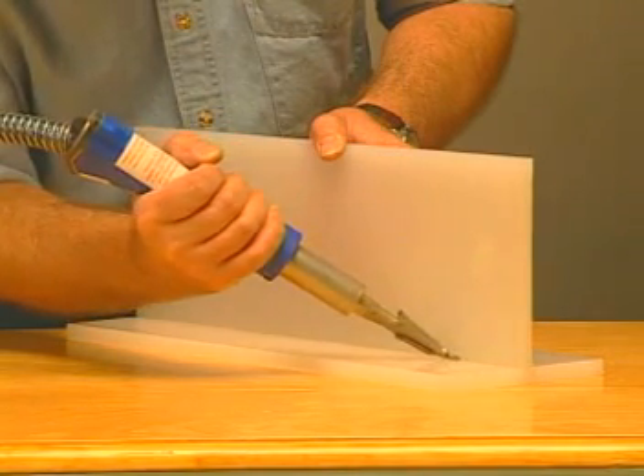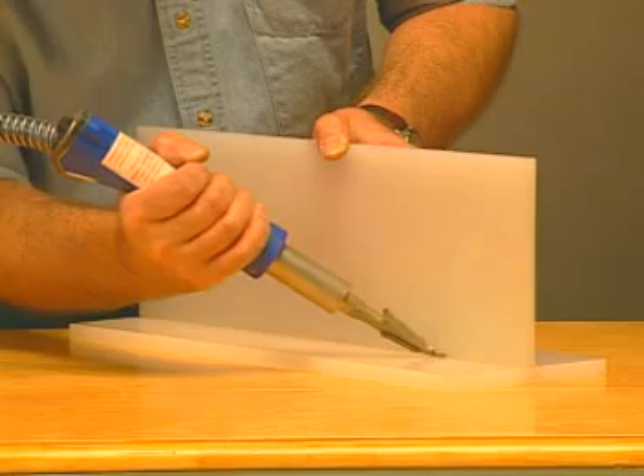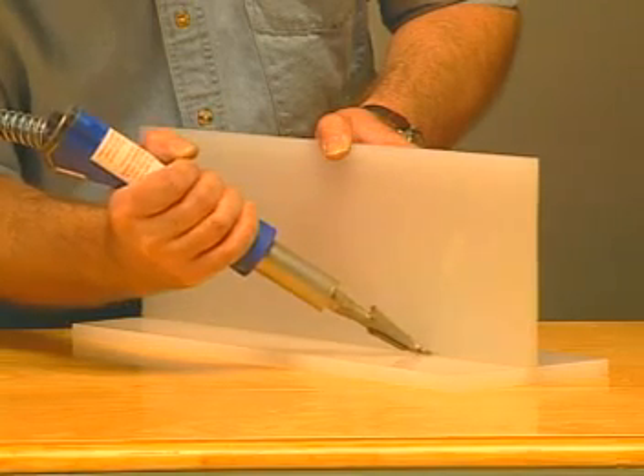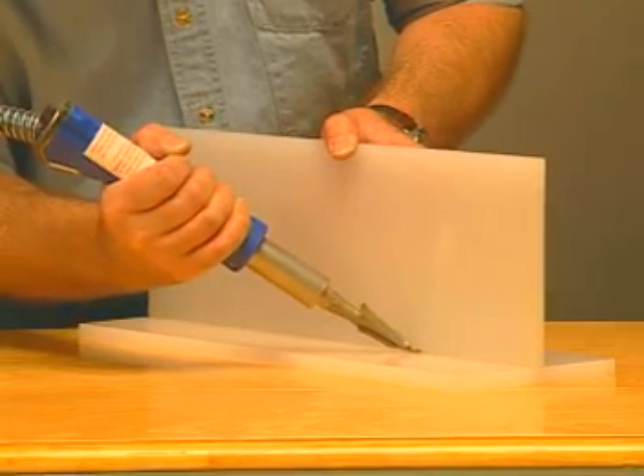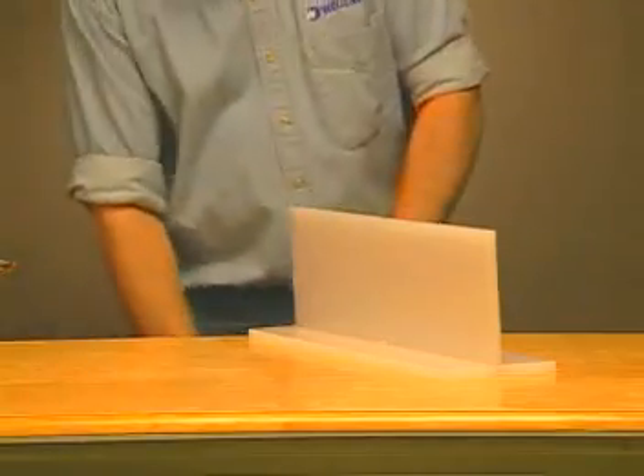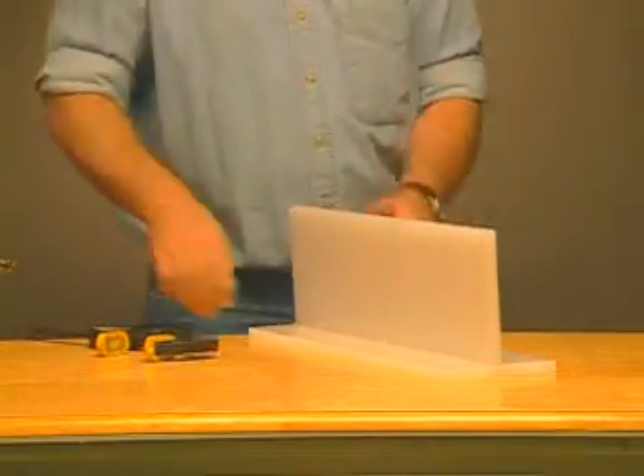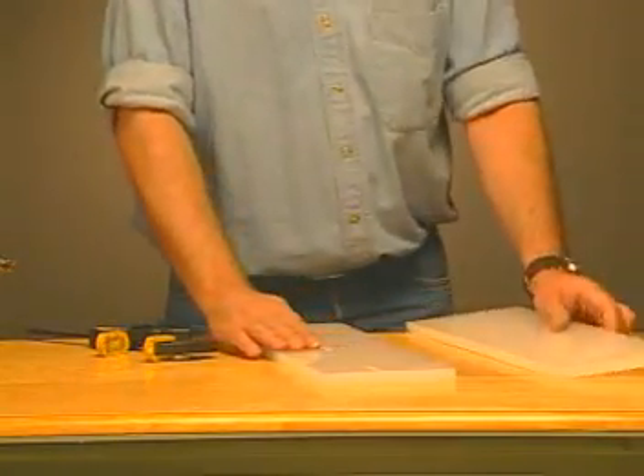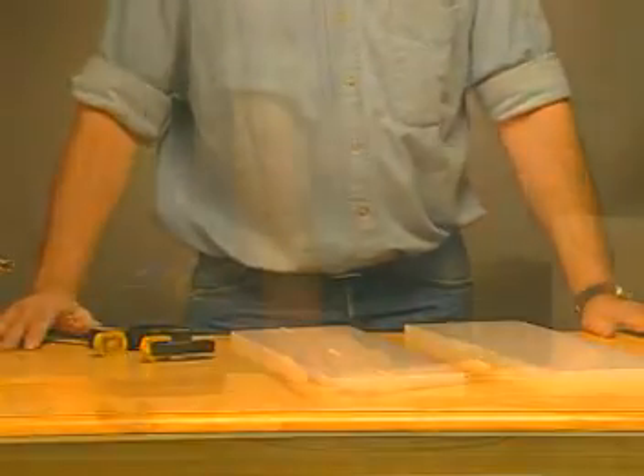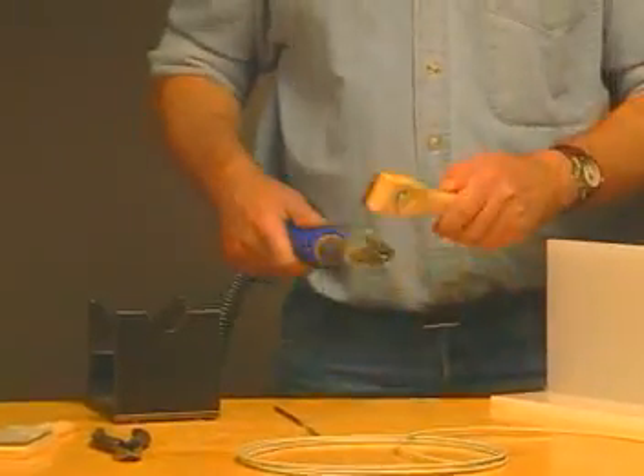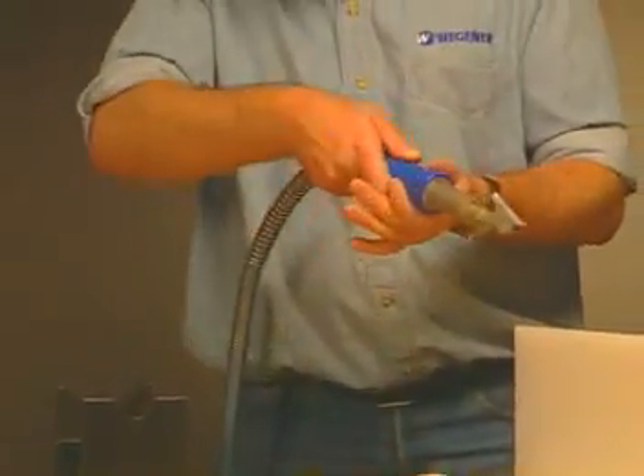In general, both sides should be tack welded to provide even distribution of heat and to keep warping to a minimum. Tacking does not add any strength. Should a piece be misaligned, a tack weld is easy to break apart, while a filler weld would have to be removed mechanically. After tacking, flip the tacking tip to the back in order to use the high speed tip.